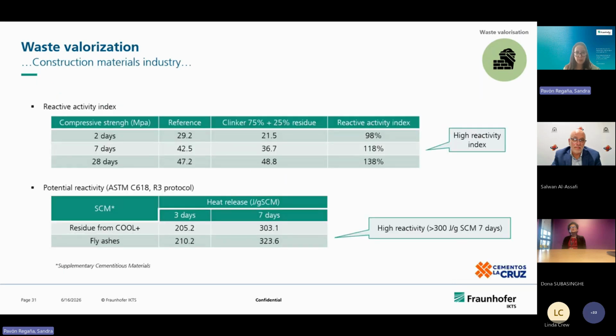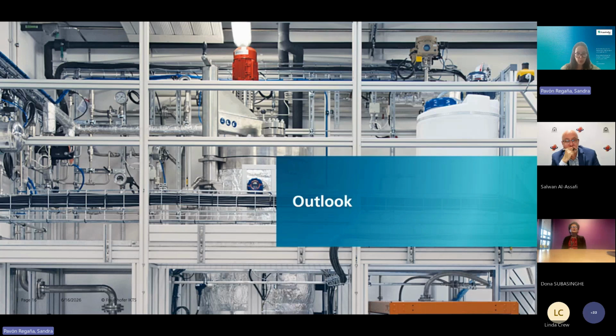And for the cement industry, we had another collaboration with another industry, Cementos La Cruz, and they were doing validation of this material, and it has a high reactivity index and high heat release compared to other materials that they are working with, like for instance fly ashes. So it's really comparable. So that means that it could be possible to work with this in the cement industry.